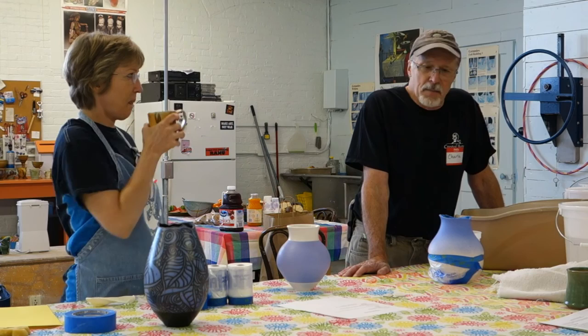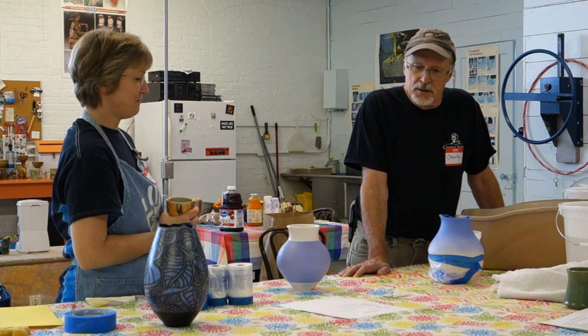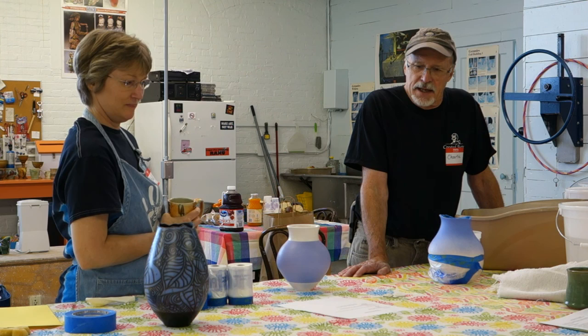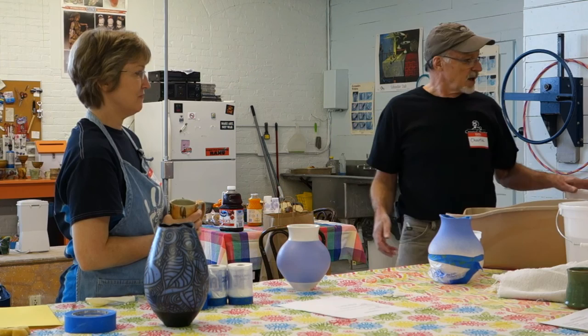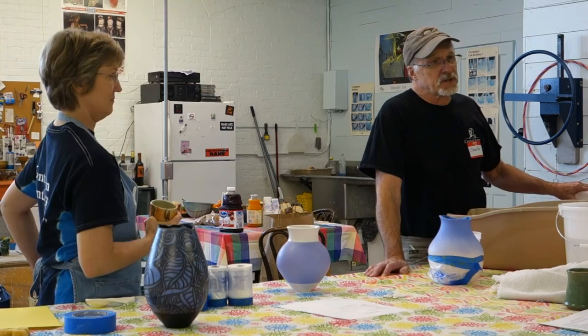In this case, I have made a batch that's about 2,000 grams of dry clay. I think it comes out to 1,200 grams of EPK and 800 of silica, so that ends up with a batch that's about a gallon and a half after you've finished it up. I'll take the dry clay, put hot water on it, and that helps the clay slake down.